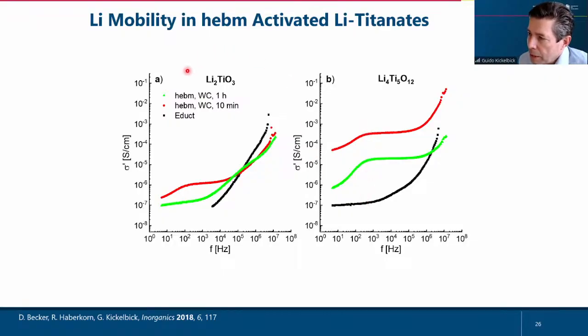And in addition, what's very interesting is that long milling does not always help. So at short milling times, the increase of lithium conductivity is much higher than with longer milling times. This is a very interesting aspect, and we see that in many different reactions that longer milling times do not always help you.